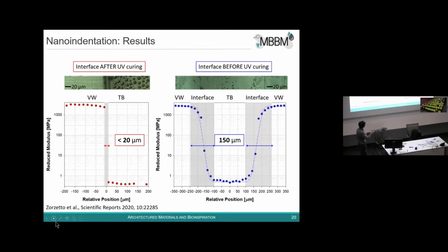And here you see that we don't see those regular blisters anymore. This is now where we indented between stiff, soft, stiff, just to acquire a few more points to see the trend of the interface. And you see that the interface is much broader, and we measure an interface thickness of about 150 micrometers, which is several times the dimension of the droplets which are deposited. So there is some diffusion, some mechanical diffusion, if you want, because of the roller, which levels the layers, plus probably some chemical diffusion.